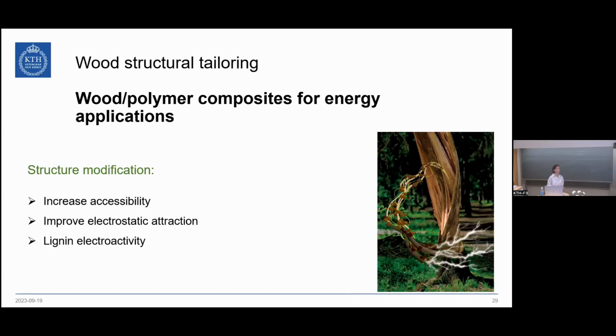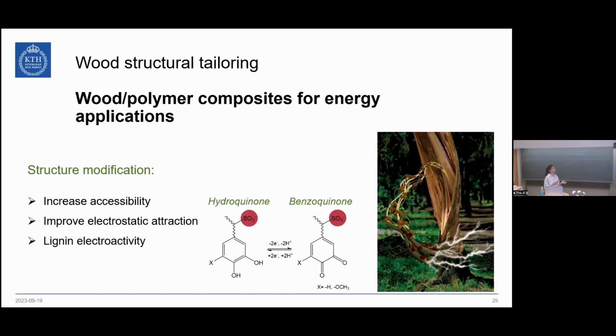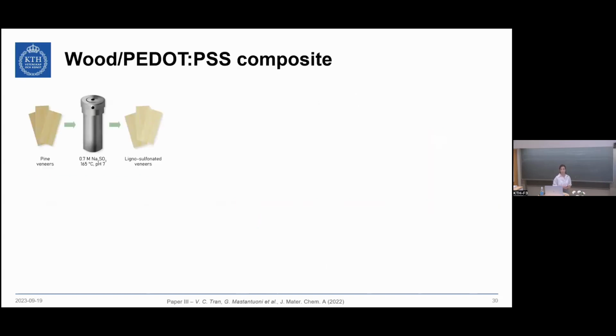Lignin is actually electroactive, and the reason for this is that it can switch between the hydroquinone and benzoquinone structure, so it can exchange 2 protons and 2 electrons. Furthermore, the sulfonate groups that we introduced during sulfonation can also act both as dopant and stabilizer for the polymer phase. So in the first case, we have wood and PEDOT:PSS composite. In this case, sulfonation was followed by the infiltration with the prepolymerized PEDOT:PSS. In this case, the particle size was around 30 nanometers.